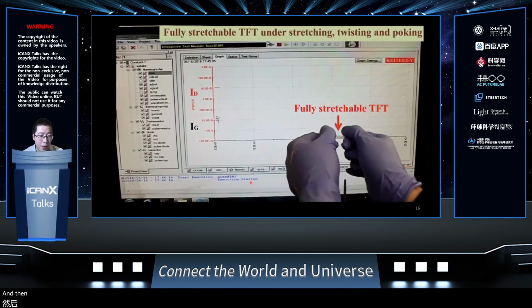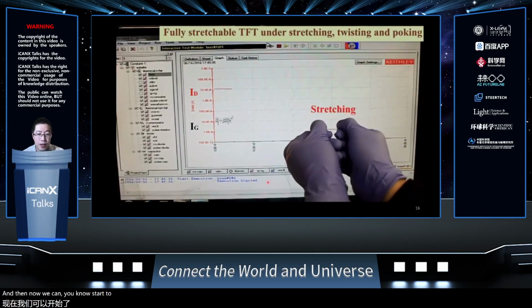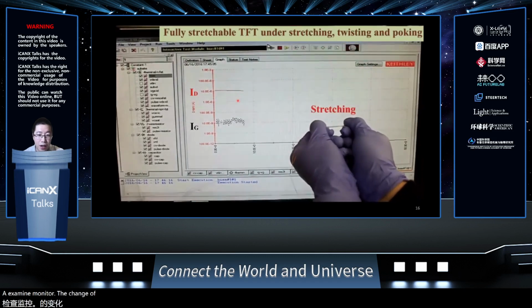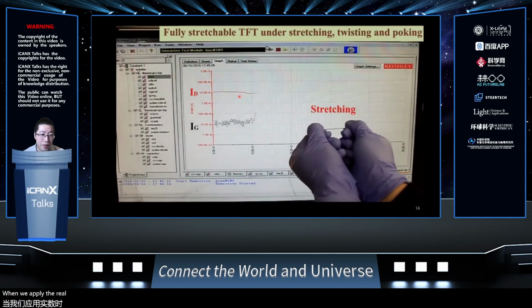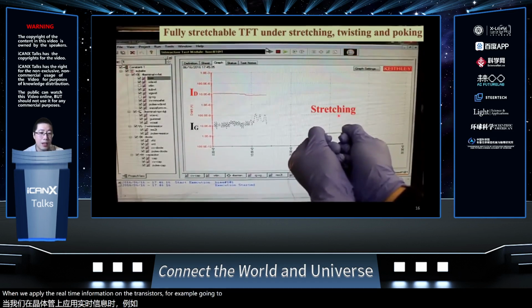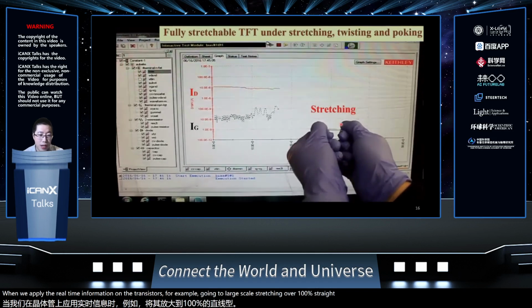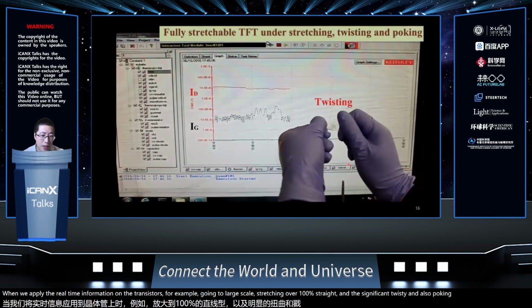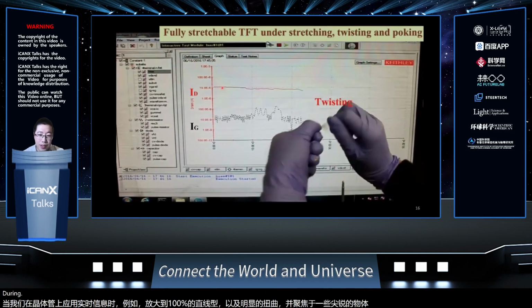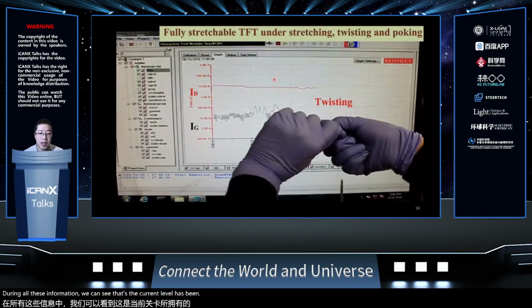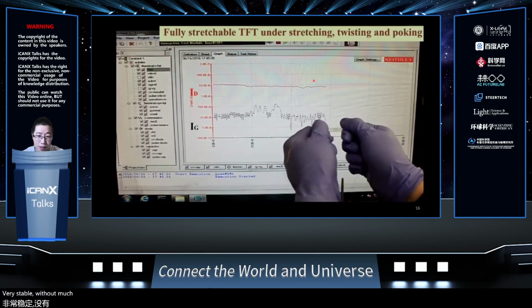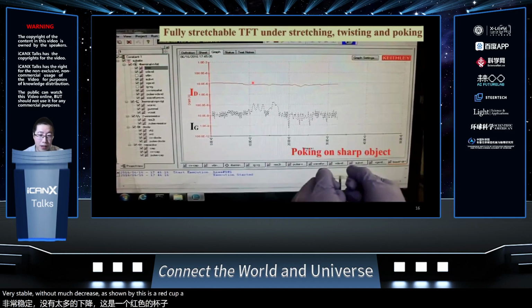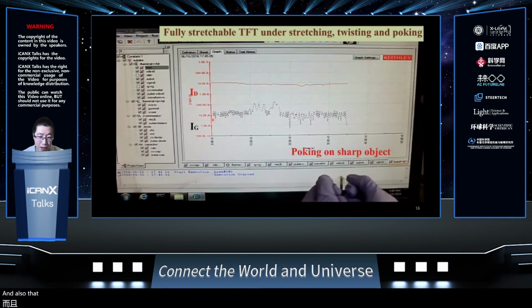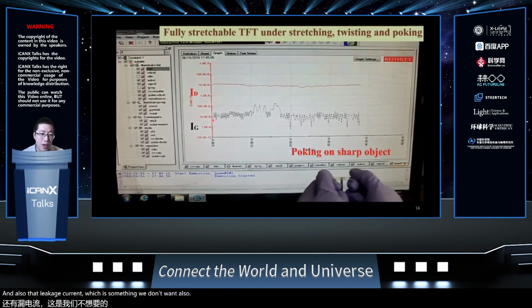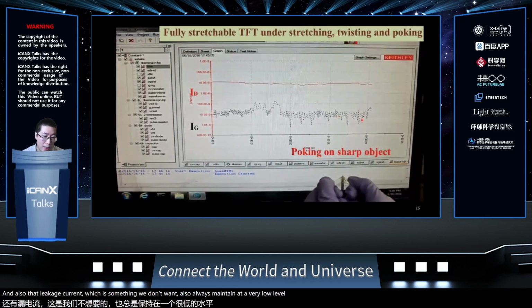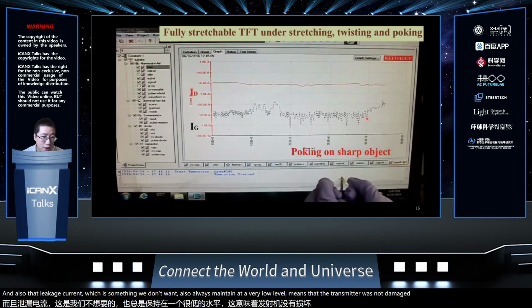And now we can start to monitor the change of the currents when we apply real-time deformation on the transistors, for example, during large-scale stretching over 100% strain, significant twisting, and also poking with a sharp object. During all this deformation, we can see that the current level has been maintained very stable without much decrease, as shown by this red line, the drain current. The leakage current, which is something we don't want, also always stayed at a very low level, meaning that the transistor was not damaged during all this deformation process.